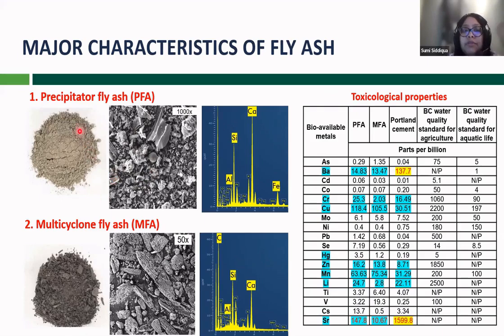So those two fly ash, that precipitator fly ash and the multi-cyclone fly ash, we have characterized using XRD, and we also looked into the toxicological properties and identified with respect to the BC water quality guidelines for the agriculture and also BC water quality guidelines for aquatic life. So these are the two reference points. And we saw that most of the properties are way below the standard given to us. And also we compared that value with respect to the Portland cement. And most of the heavy metals we have seen in the fly ash, we found that those are either close to cement or much lower than cement properties.